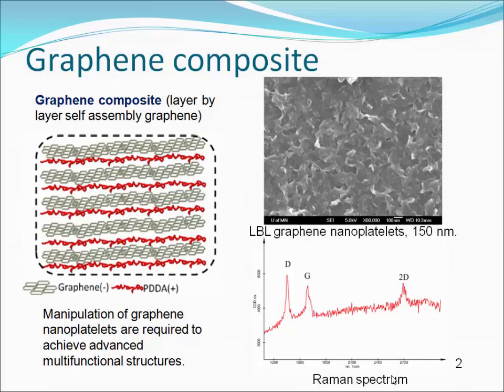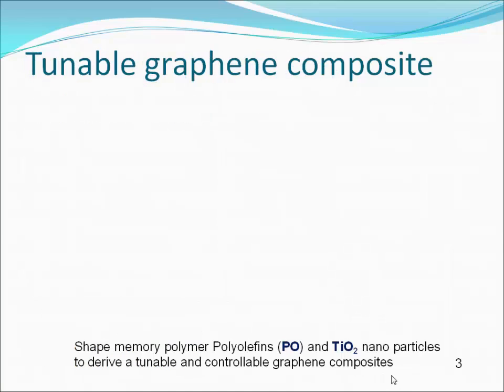The graphene nanoplatelets are about 150 nanometers in size. And this Raman spectrum has a prominent D peak here because the edges of the graphene nanoplatelets introduce a lot of defects. Most of the graphene composites reported so far are not tunable because of their synthesis process or because of their fixed structures. So we try to use shape memory polymer PO and titanium oxide nanoparticles to derive tunable and controllable graphene composites, even after the synthesis process. This is how we did it.